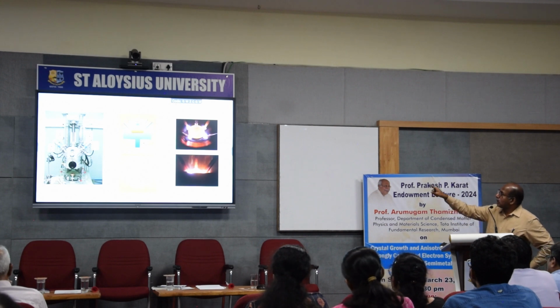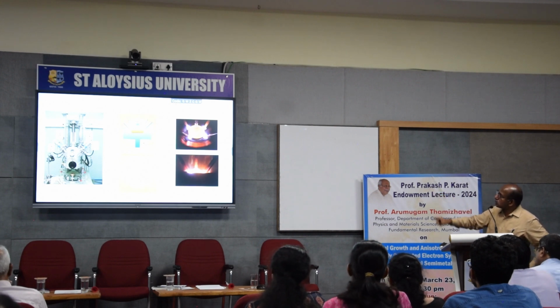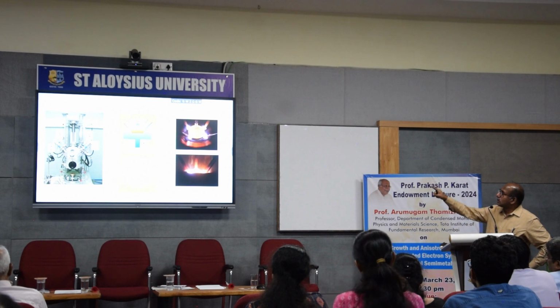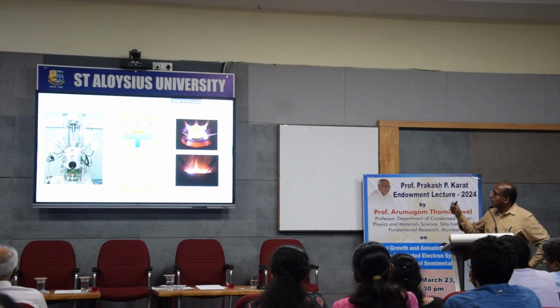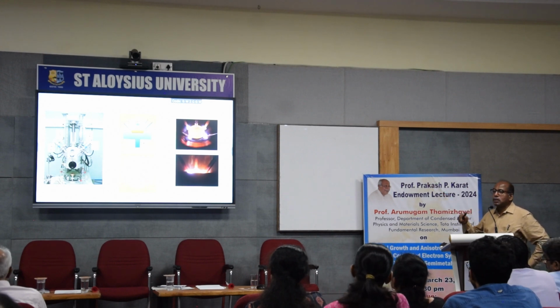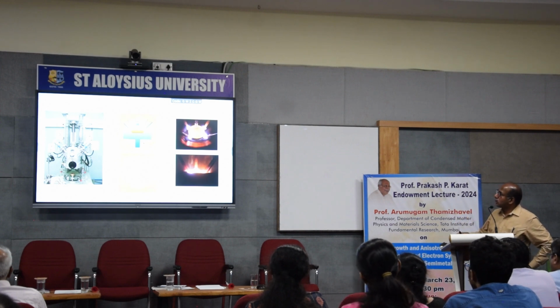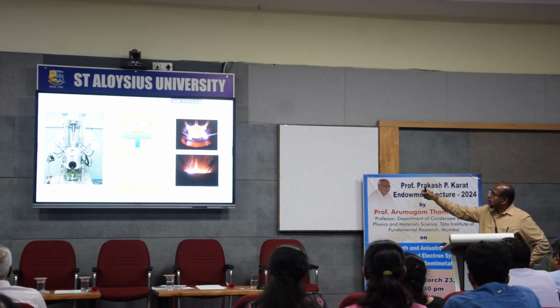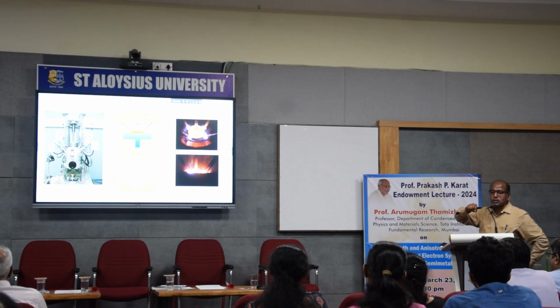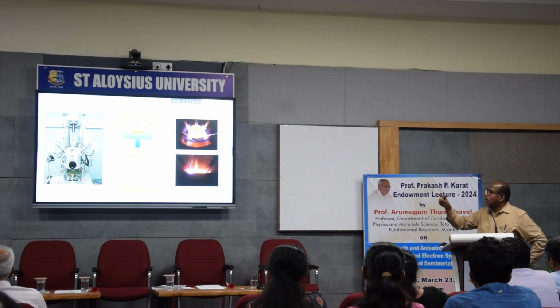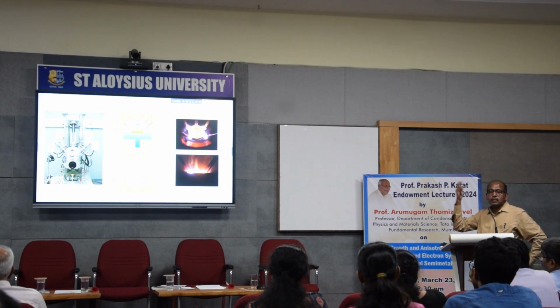So that's how I can melt samples whose melting points are very high using the 4 electrodes. I melt the sample multiple times to make it homogeneous, and then cut a polycrystalline sample and insert it into this molten solution. The seed crystal is coming from room temperature. Here the sample temperature is say 1500 or 1600 degrees centigrade.